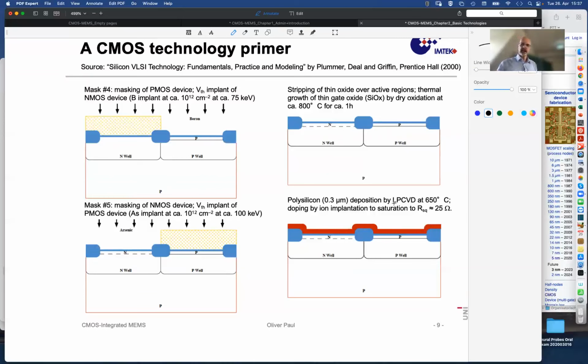It's deposited again at low pressure by chemical vapor deposition of some silane or mono, bi, or trichloro or tetrachlorosilane. There are different processes at this reasonably low temperature, and at that temperature, the silicon that is now dissociating from that chemical gases compound settles and crystallizes in microcrystalline structure, and then those structures grow. And so at the end, you have some polycrystalline structure that constitute your gate material.